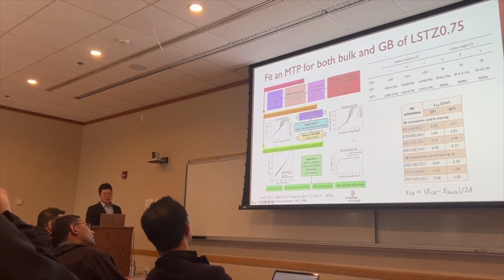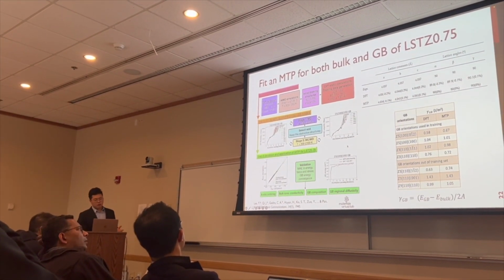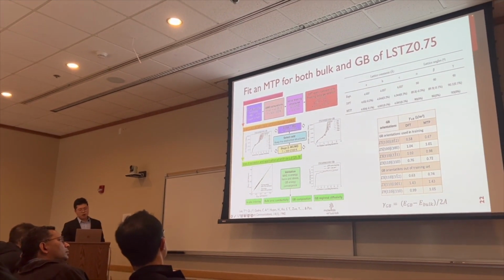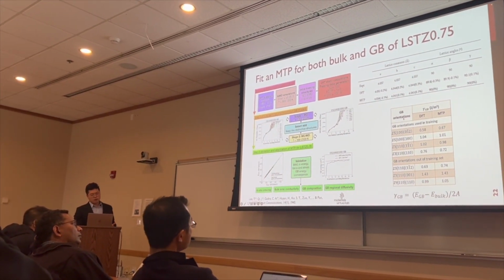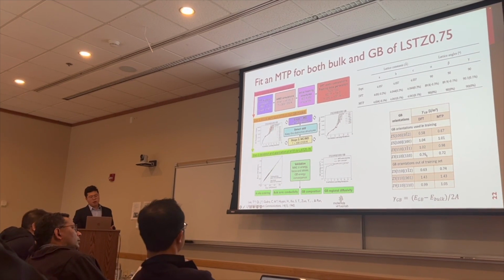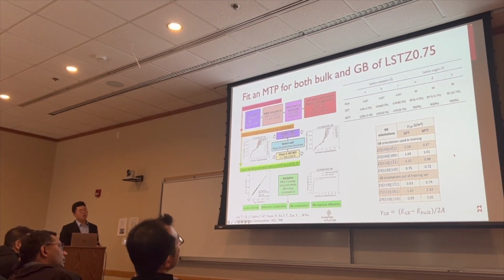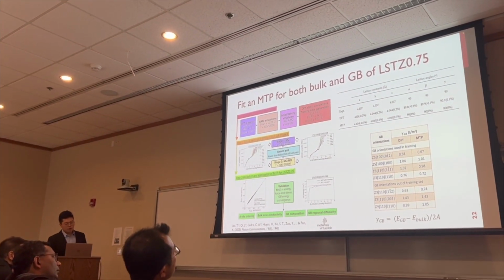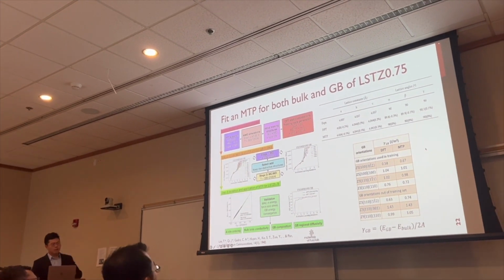And an additional verification is done for the grain boundary energy simulation that is out of the training set. So for those grain boundary orientations, we got reasonable error below 0.15 joule per meter squared for those grain boundaries we simulated.